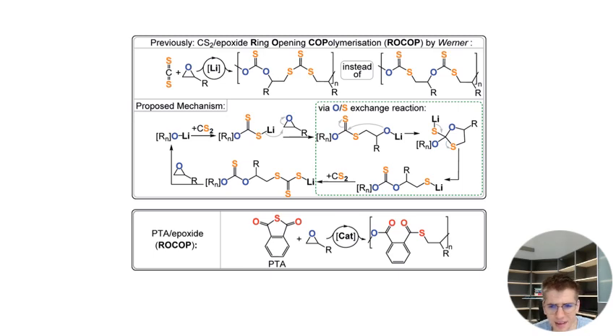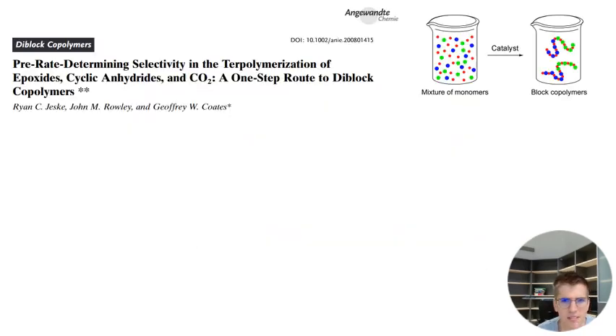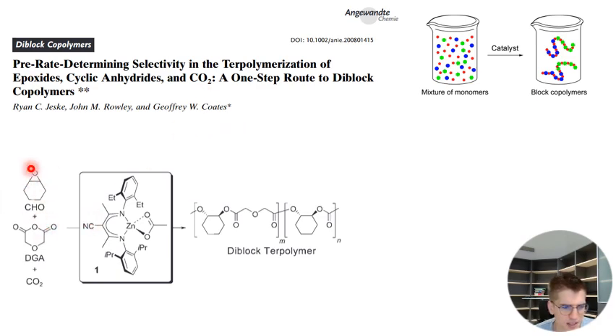And when I started independently in the lab, I had done a postdoc before in a research group which were doing these copolymerizations exclusively with oxygenated monomers. And so CO2 and not thioanhydrides but anhydrides. And there was a paper from 2004, 2006, does it say it here? No. From the Coates group, which mixed an epoxide, now it is cyclohexene oxide, with CO2 and again such a cyclic anhydride and this somewhat optimized zinc catalyst here. And the copolymerization of this anhydride and the epoxide would give you a polyester like here, and the copolymerization of the epoxide and CO2 would give you a polycarbonate like here.